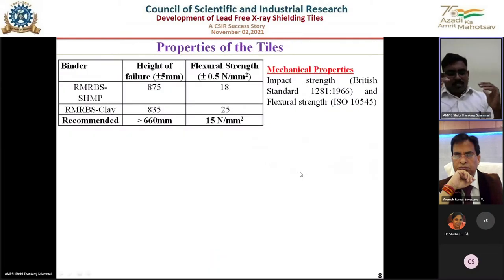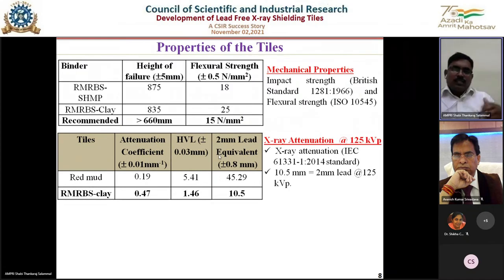So then the other important property is attenuation. Then the properties of the tiles, like their strength, for example height of failure, that's impact strength, and flexural strength. So we have tested our clay tiles, and they are giving good strength, so they are suitable for construction applications. Then we have also tested its radiation shielding characteristics as per the IEC standard 61331. And as per this, a 10.5 mm thick tile possesses the lead attenuation equivalent to 2 mm lead.